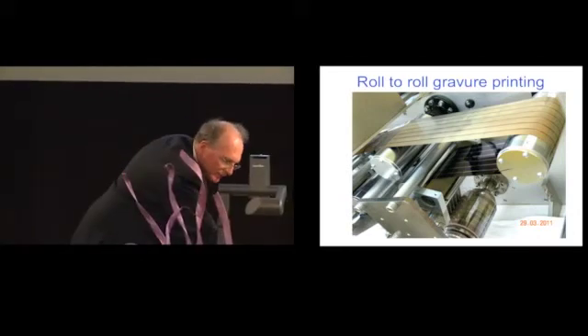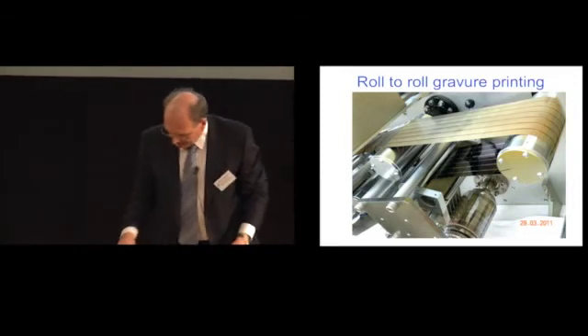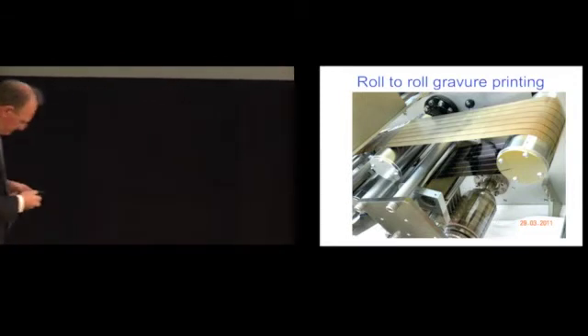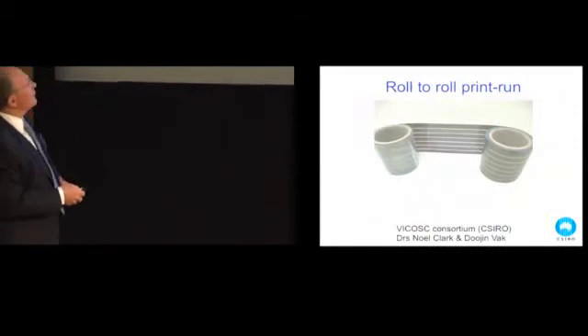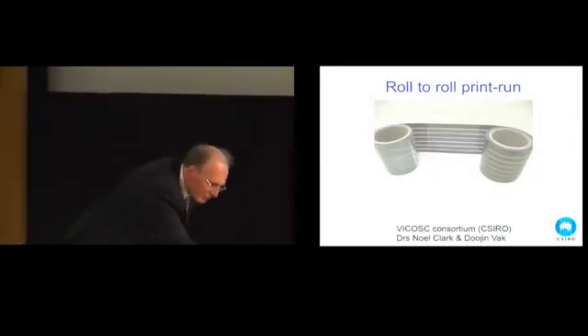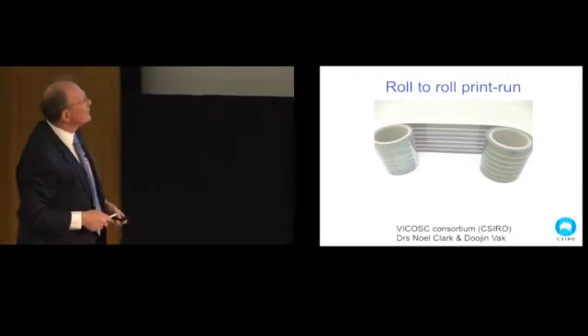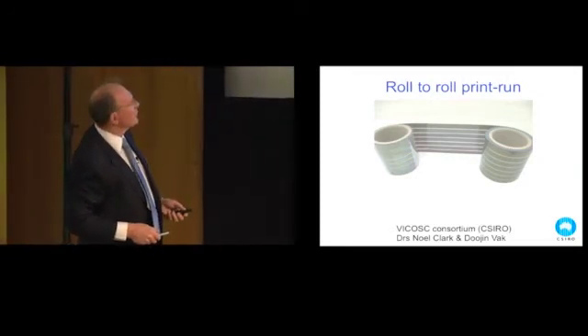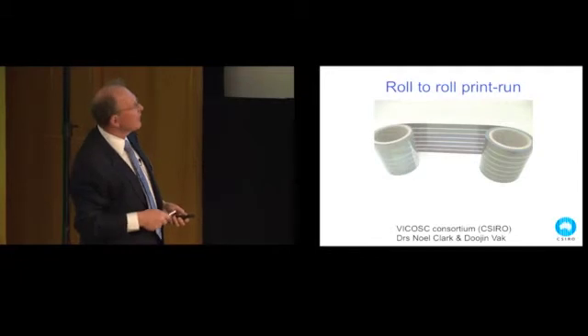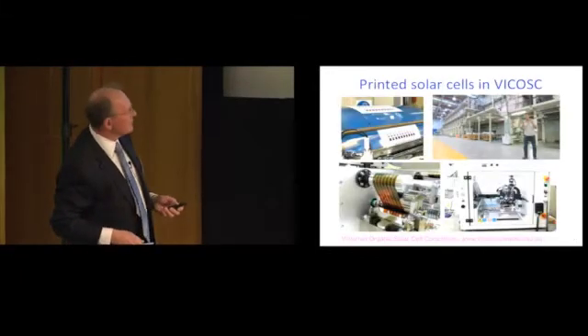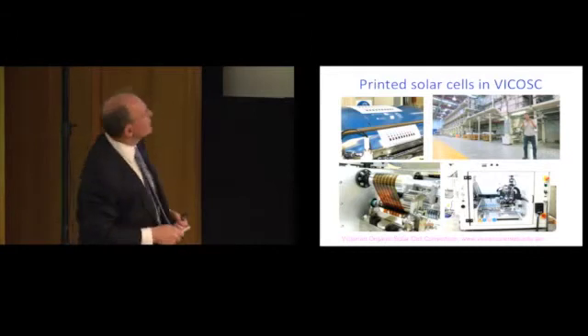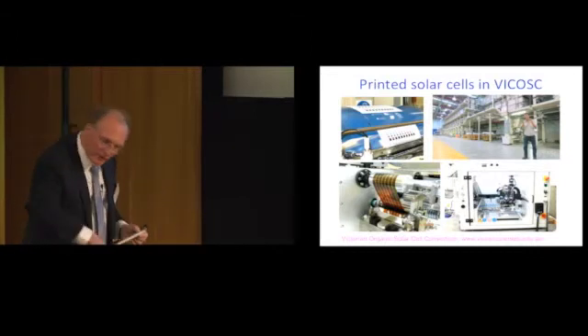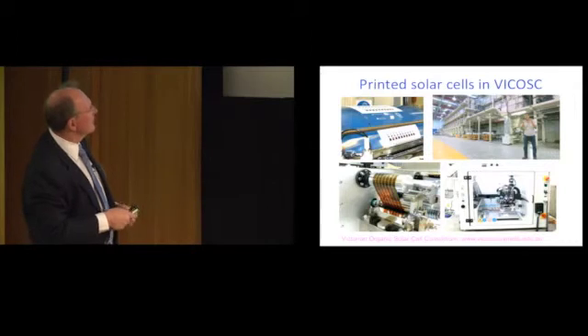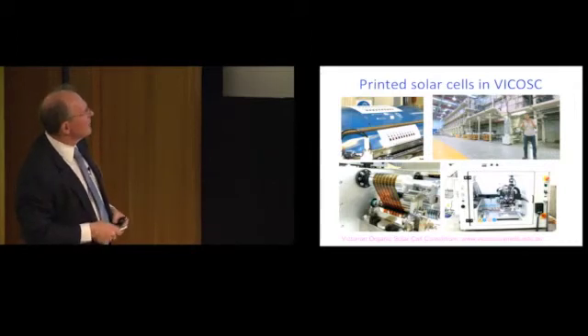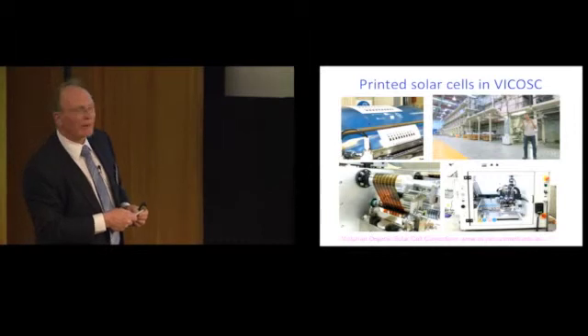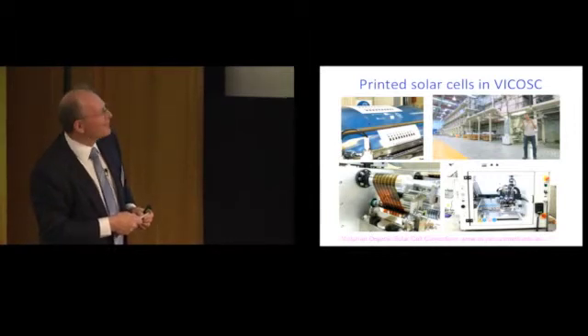I need to put on the power to illustrate this in a minute. So that's the film I showed you of the printed polymer film. And it needs just one more layer of electrode to make a solar cell. So we can print this, and as I said, with that fullerene, we can print 1,500 square meters of that. So we first printed with just a rotating proofing press. Then we used this mini labo press. This is where the Australian money is printed, and they won't let the photographer get any closer to see the technology.